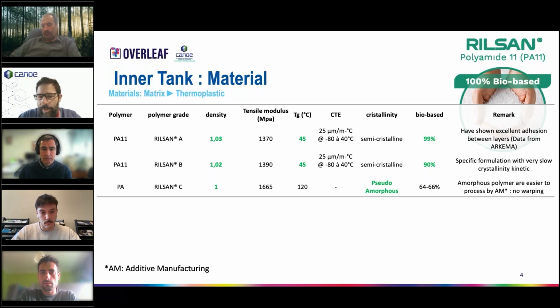The first one shows excellent adhesion between the layers during the printing process, which is a pretty good thing. And the second one has a specific kinetic during the crystallization. You have to know that crystallization rate is a pretty important part of the 3D printing process in order to control the warping effects. Then we tried another polyamide. It's an amorphous one, called Rilsan Clear. This material is not 100% bio-based, but anyway, it works as well for additive manufacturing. This one was chosen for the development because it's an amorphous one, so there are no crystallization parameters to control, and it should be easier to process.